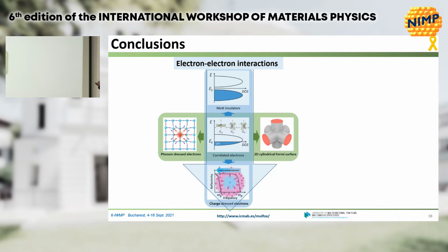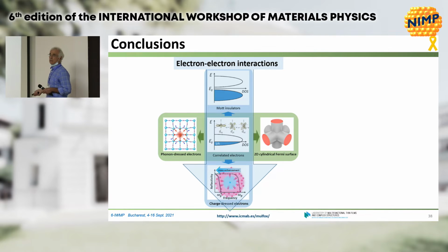Summarizing, I start from the idea of electron-correlated matter or electron-correlated electronic systems in these materials. I end up with a situation in which the best description, or better description, is given in terms of electron-phonon coupling and anisotropy of the Fermi surface and the multi-orbital character.